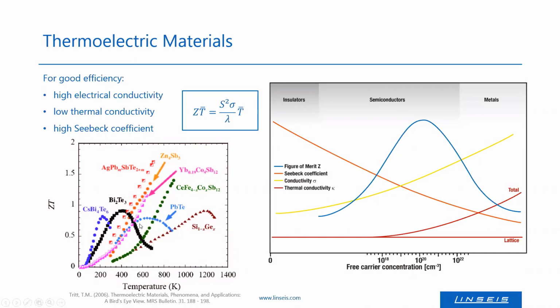On the left here, some thermoelectric materials are shown with their performance evaluation and dependence on temperature. So for example, one can see here the commonly used bismuth telluride, which shows here the figure of merit in dependence on temperature, as well as some alloys of bismuth telluride. One can see zinc antimonide here in orange, or silicon germanium here in red to brownish color. And one can see here clearly that different materials have different figures of merit, and the figure of merit strongly depends on the temperature.